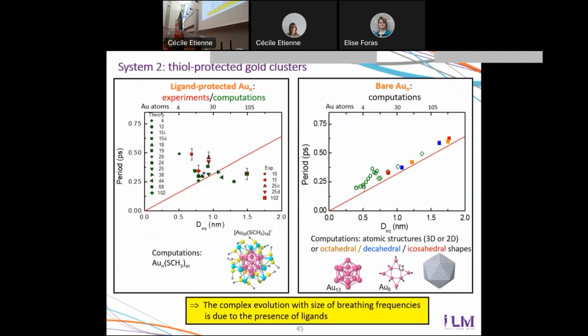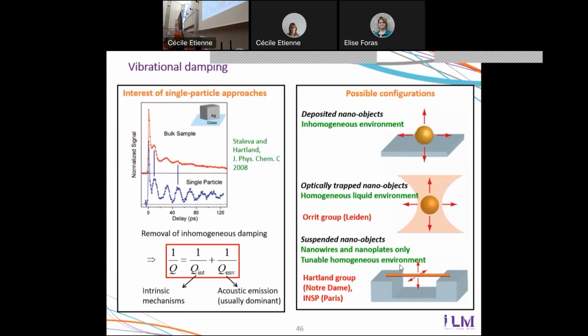So in that sense, the conclusion of this part is that elasticity is a property that is very robust towards size reduction. Elasticity of small nanoparticles is still, at least in this experiment and for these vibrational modes, the same as that of a much larger object.